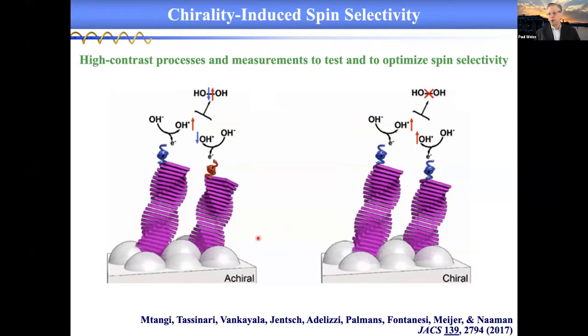And to me, the experiment that really showed the effect most strongly was this one, in which one is doing water splitting, and a side reaction of water splitting is hydrogen peroxide production. That can only happen actually with a singlet. If one produces a triplet for water splitting, one cannot make hydrogen peroxide. And so what Ron did with Bert Meijer was show that by controlling the spin coming out in these systems, they could turn on and off the side product. So it's really the first case where it was completely on and completely off. One can argue about what the quantitative effects were in many other cases, but this one I think really nailed it. One can't argue with the result.